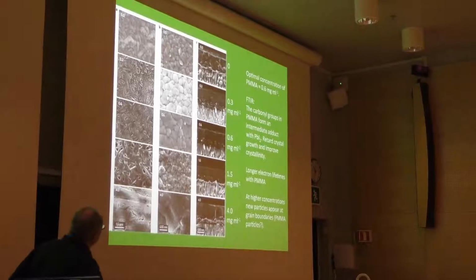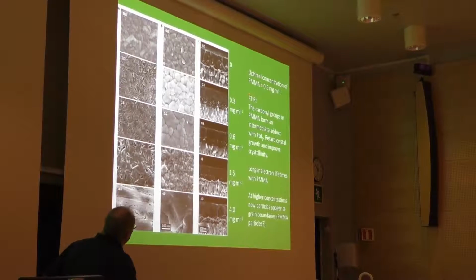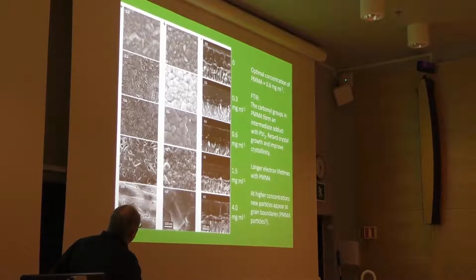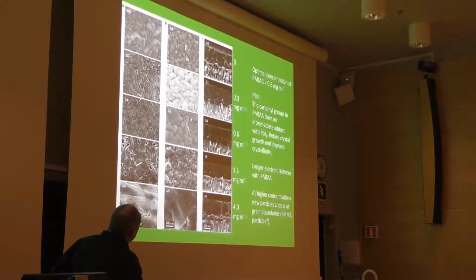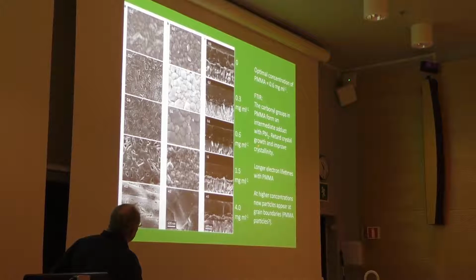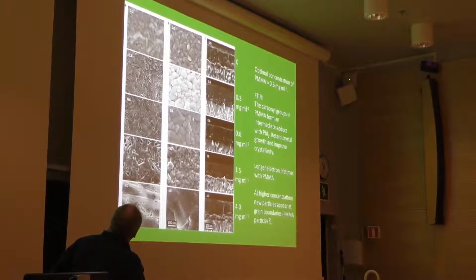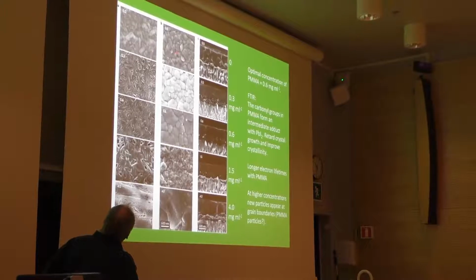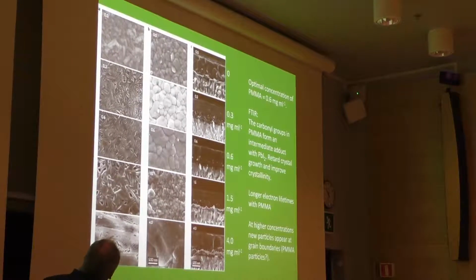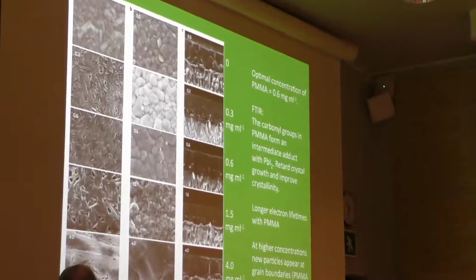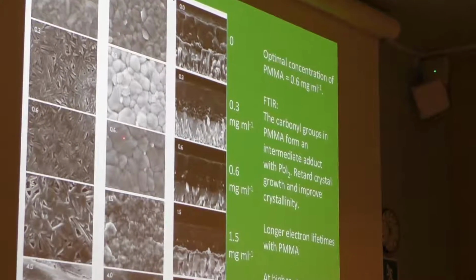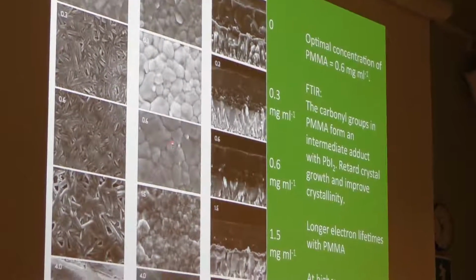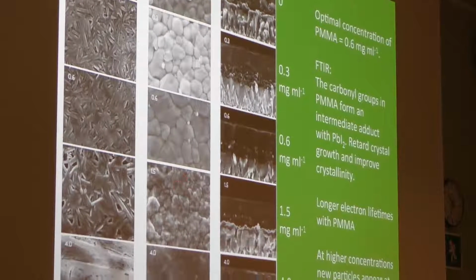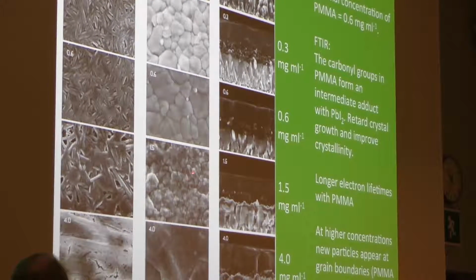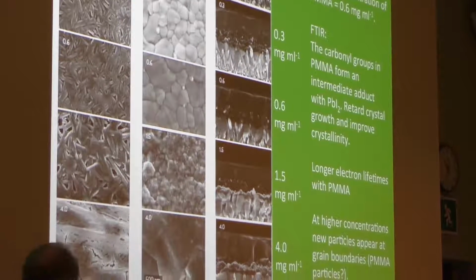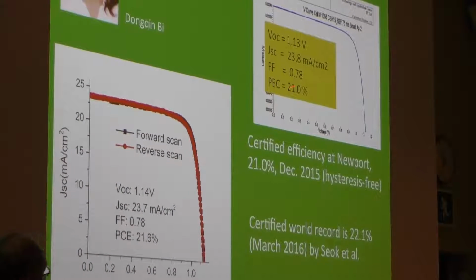What you see here is what I said about the PMMA additive. We can see that we form an adduct, a complex with lead iodide. It retards the growth and improves crystallinity. So this is without PMMA: smaller crystals. We enlarge them with some PMMA. This is the optimal concentration of the PMMA: larger crystals, fewer grain boundaries. At higher concentration, we seem to have a precipitation of the PMMA, and it doesn't work anymore. So the result here, we had 21.0%.